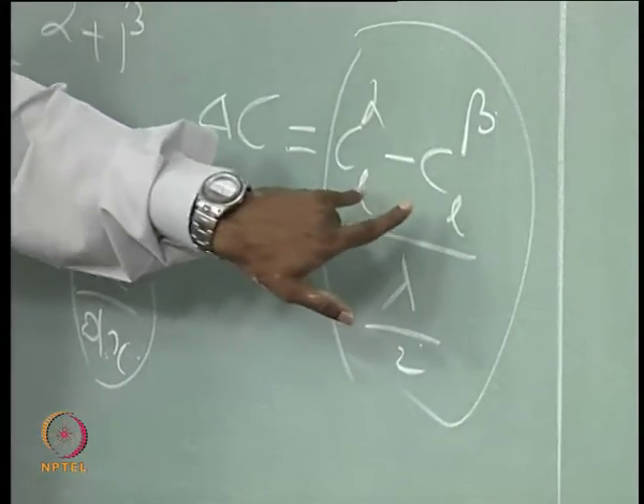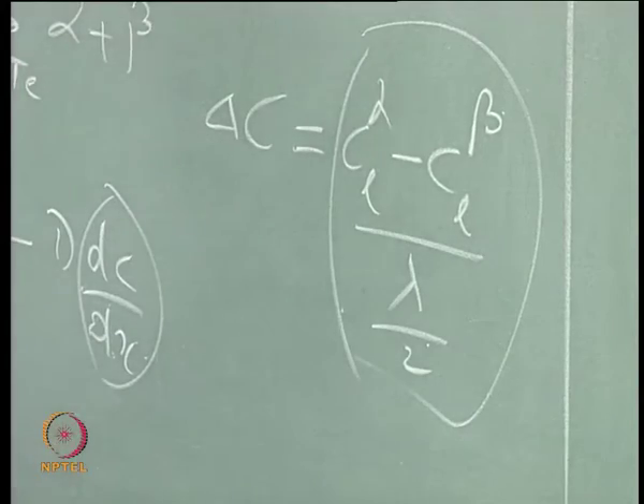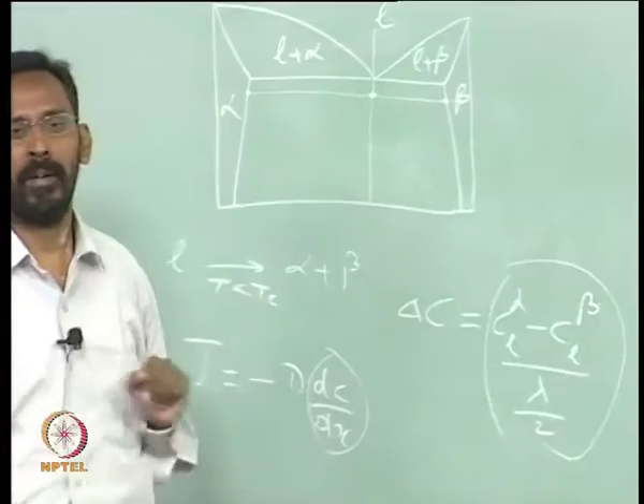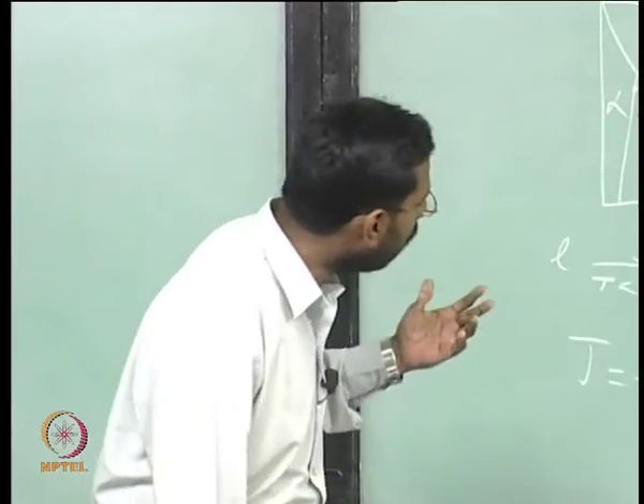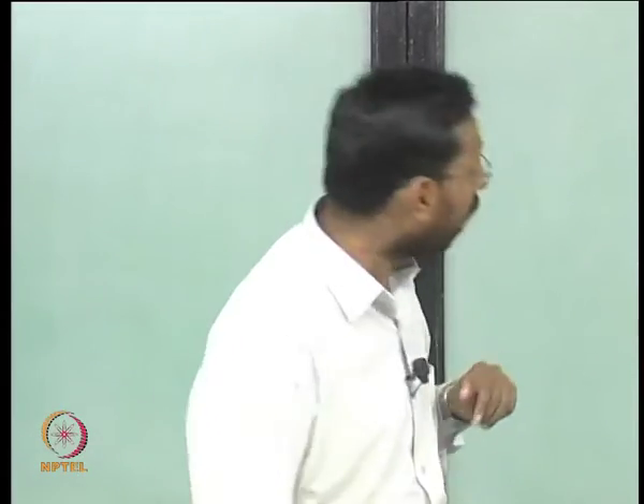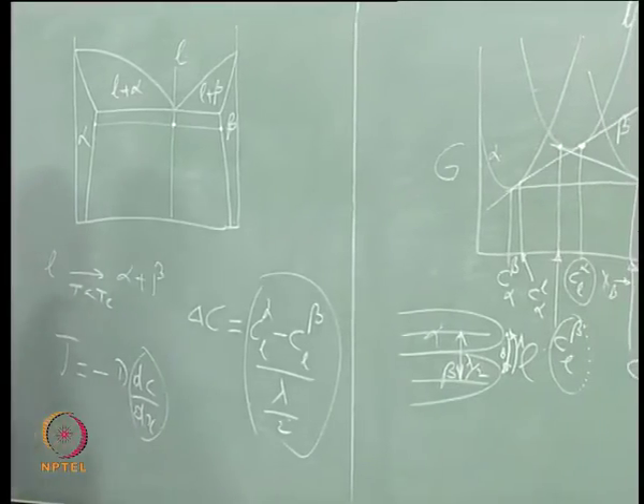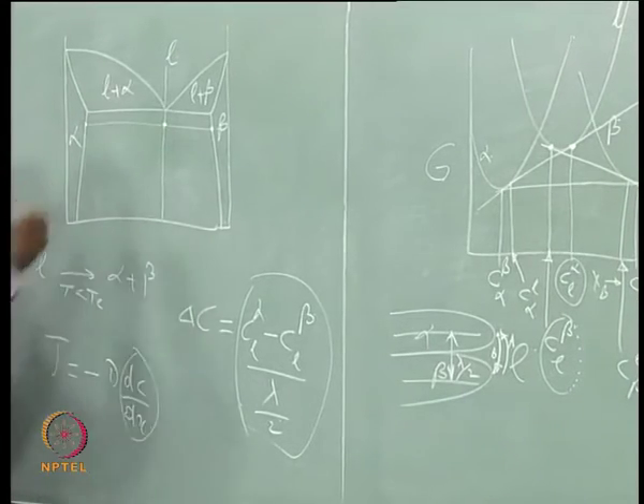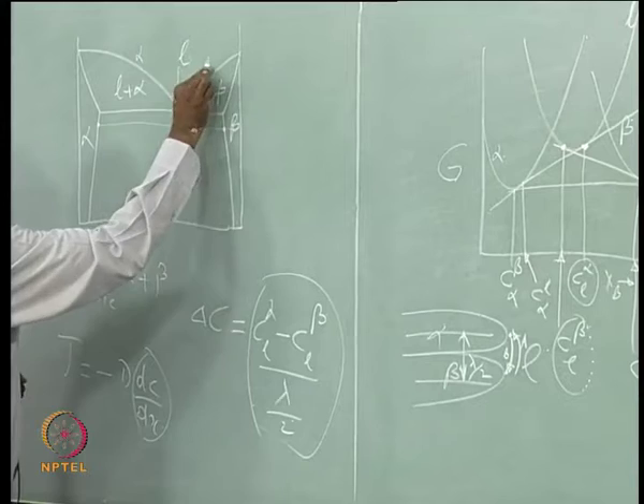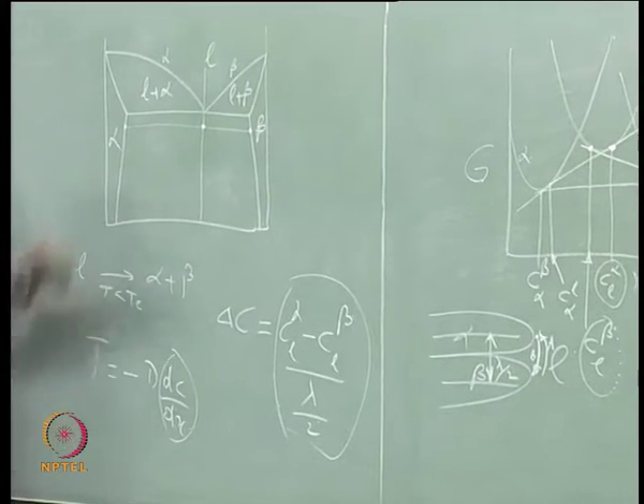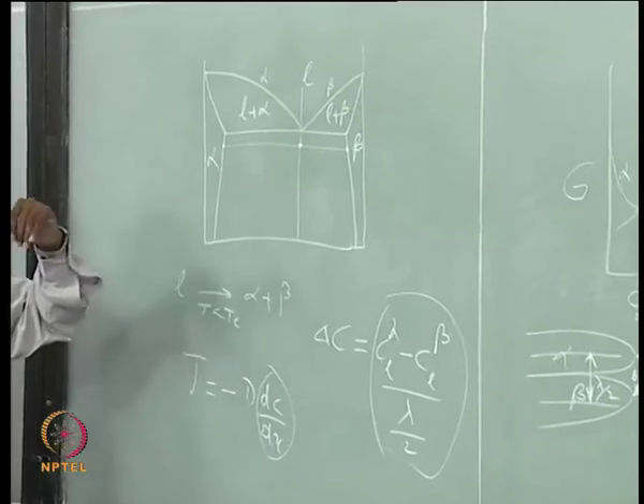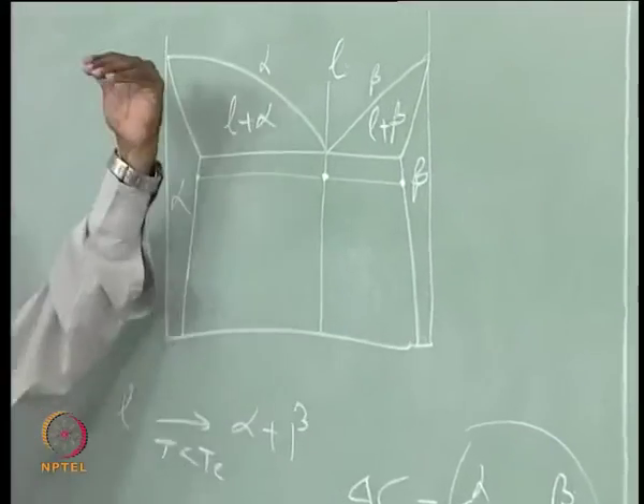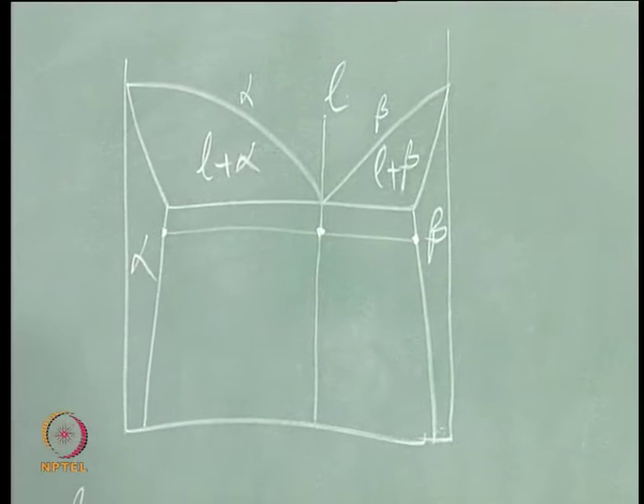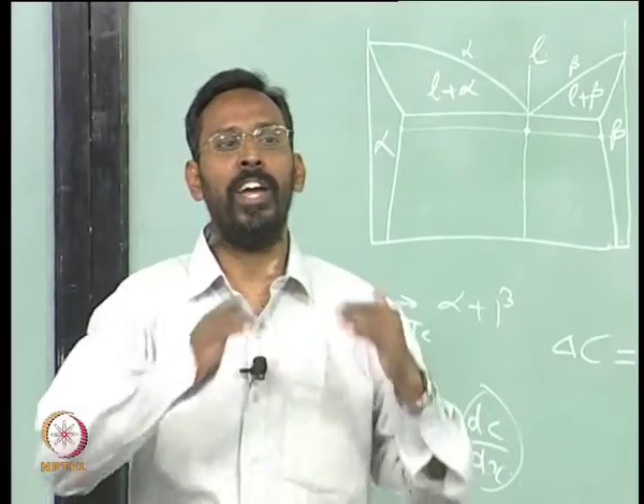And how do I see this in the phase diagram? Can I see these two points in the phase diagram? Now C liquid alpha and C liquid beta, where are they in the phase diagram? Extrapolate. Yes, so you have two liquidus here, one is called the alpha liquidus, another is called the beta liquidus. What does alpha liquidus tell you? Alpha liquidus tells you at all temperatures what is the composition of liquid in equilibrium with alpha, and the beta liquidus tells you the composition of liquid in equilibrium with beta at various temperatures.